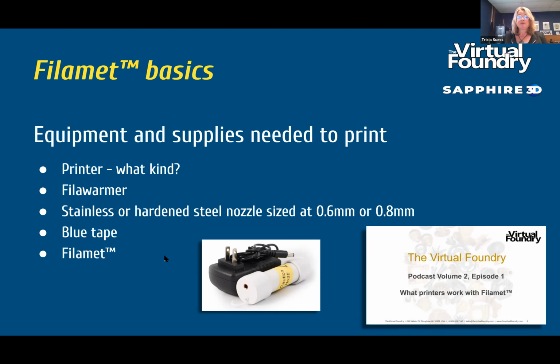And you'll need a stainless or hardened steel nozzle sized at 0.6 or 0.8 millimeter, a Filawarmer, and you do need to manage bed adhesion because Filamet really sticks to the print bed. So on a glass surface, you can use a glue stick. On every other surface, we recommend using blue painter's tape. And then you'll also need your filament. So that's it. You're not making any modifications to your printer aside from getting that harder nozzle.